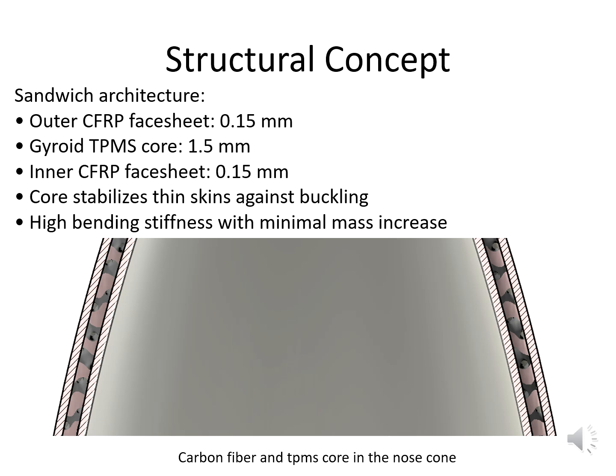One of the major advantages of TPMS cores is that their stiffness and density can be tuned simply by adjusting the relative density parameter. This allows us to tailor the mechanical response to match specific mission requirements without changing the outer geometry. The combination of these skins and the lattice results in a structure that is exceptionally stiff for its weight and inherently resistant to local buckling. This makes it an excellent candidate for components like nose cones, which must withstand aerodynamic pressure and vibration while remaining very light.